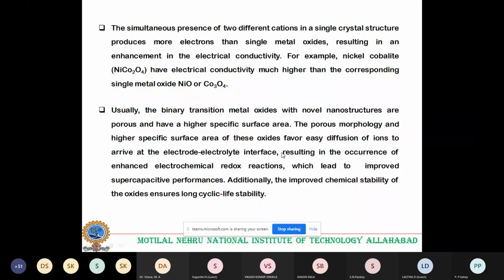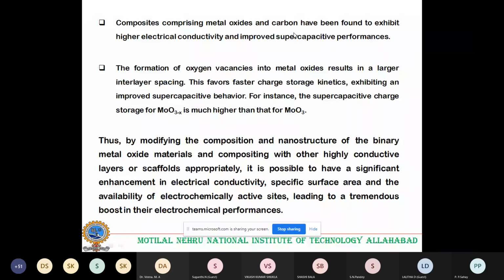Third, a composite comprising metal oxide and carbon. Carbon has good electrical conductivity. So if you make a composite comprising metal oxide and carbon, it has been found to exhibit higher electrical conductivity and improved supercapacitor performance. The last, the formation of oxygen vacancy in metal oxide results in a larger interlayer spacing.